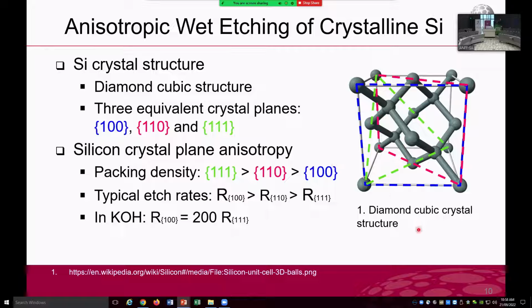This diagram shows a unit cell of the diamond cubic crystal structure. We can see 3 equivalent crystal planes. This is the 100 plane in blue, the 110 plane in red, and the 111 plane in green. These 3 equivalent planes show different atomic packing density. Can you see that? The packing density is different on different planes. This can lead to a different etch rate in a certain type of etchant.